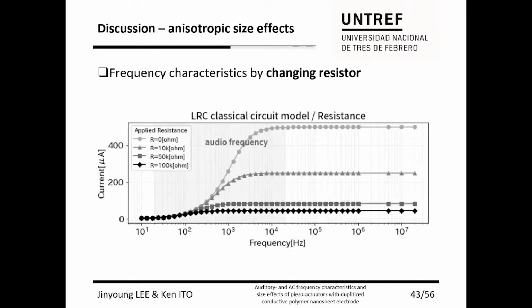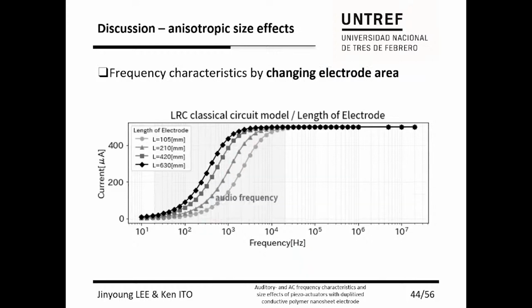We next check the theoretical behavior with resistor and capacitor as parameters. As the resistance decreased, the plateau current value increased in the high frequency range, and the inflection point moved slightly to the high frequency side. In contrast, in the model in which only capacitance is varied, the effect of the capacitance approaches 0 farad as frequency increases, so the value of current is determined only by resistance in the high frequency range. On the other hand, in the audio frequency range, the sigmoid inflection point shifts to the low frequency range as the capacitance of the actuator increases.